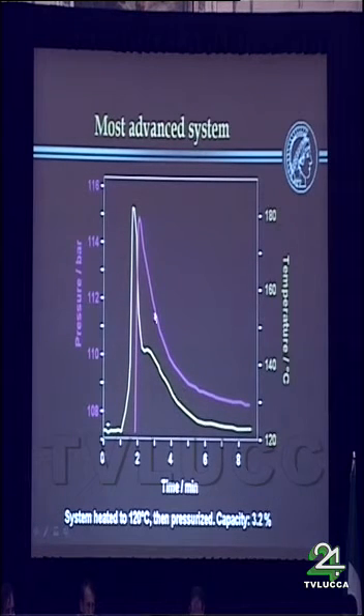This is our most advanced system. I can't tell you what it is, but this is the quickest system we have, and I would say that this has basically met the requirement of fast rehydrogenation. I think the system is basically heat transfer limited. The yellow curve is the temperature, so the system was heated to 120 centigrade, then was pressurized with 110 bars roughly of hydrogen, and you see you have a temperature overshoot to 180 centigrade.